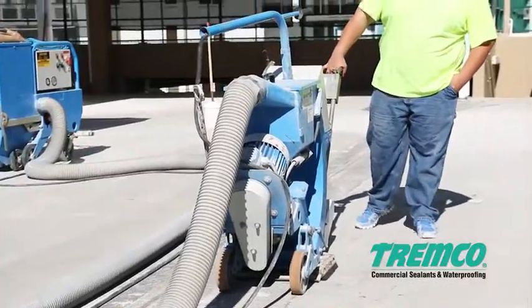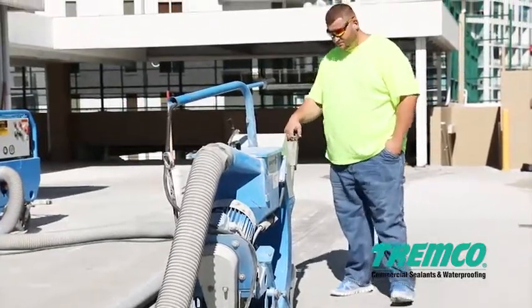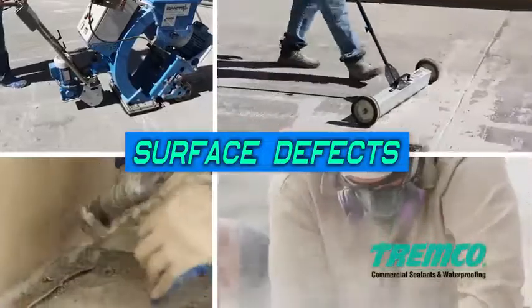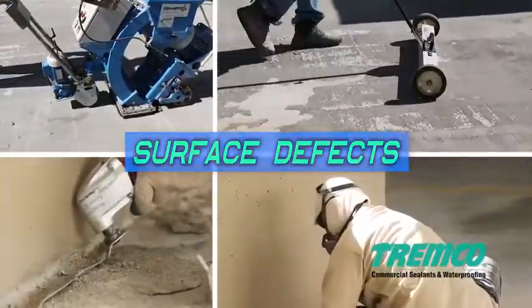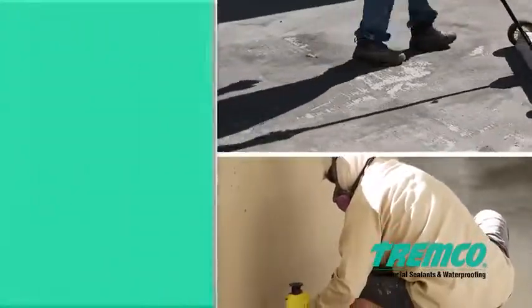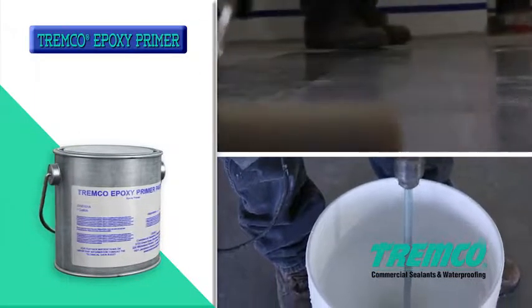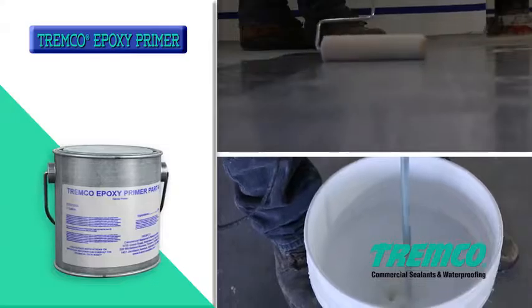Surfaces must be free of defects that may telegraph and show through the finished coating. Surfaces that are rough, such as fins, ridges, exposed aggregate, honeycombs, and deep broom finishes, must be leveled and made smooth by applying a coat of Tremco epoxy primer, sanded, or equivalent filler material.